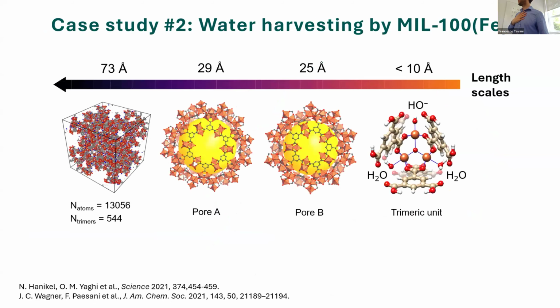Okay, so let's consider the same MOF, always MIL-100, and we're interested in investigating the mechanism of the water harvesting ability of the same MOF, because this is also a water harvesting MOF. So if we again look at the structural properties of the MOF at increasing length scales, we start from the trimeric unit. We know all about that now. Then we have two different pore windows. There's a pore A with a 29 angstrom diameter and a pore B with approximately a 25 angstrom diameter.